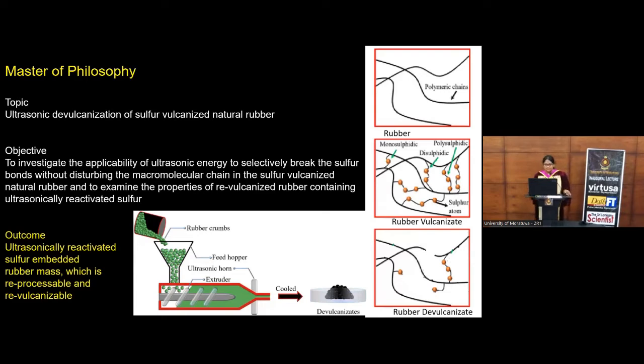Then I started a Master of Philosophy degree, again on rubber-based research. The topic was the ultrasonic devulcanization of sulfur-vulcanized natural rubber. In this research, high-energy ultrasound is used to selectively break the bonds, specifically carbon-sulfur and sulfur-sulfur bonds in the sulfidic linkages, without disturbing the carbon-carbon bonds in the main macromolecule. The outcome was a re-processable rubber mass. During sonication, the sulfur that is utilized in the crosslinks is released into the rubber mass, and that sulfur was enough to re-vulcanize the same rubber mass without adding additional vulcanizing materials.